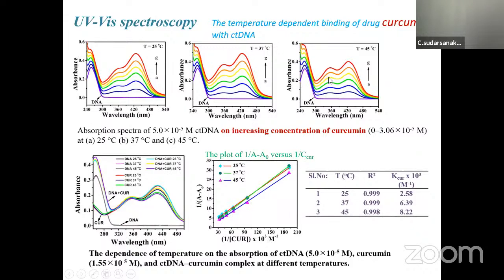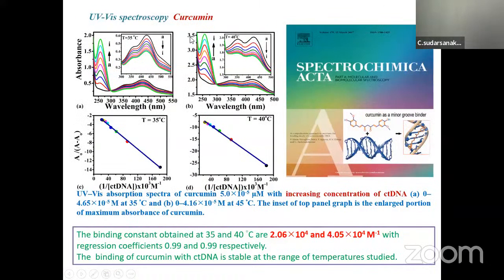This is the temperature dependent UV visible absorption spectra of curcumin. It shows a peak nearly around 420, a little above 420, that varies with different concentrations of curcumin. So this is one of the ways to look at the binding propensity.